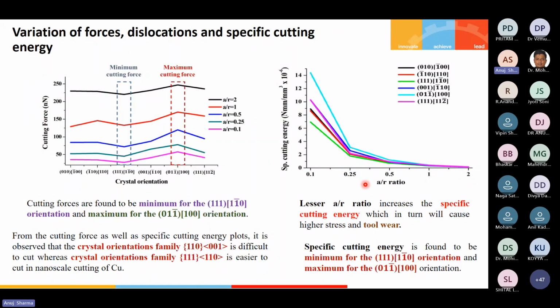Similarly, if we check the variation of forces and cutting energy, we can see that the maximum force took place for the 011 and 100 orientation, and minimum for 111 and 110 because it denotes the slip system. So it is very easy to deform in this orientation. There, the minimum amount of force is required to deform the material.